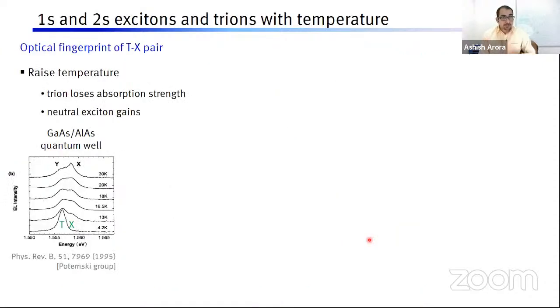For that, we use something well known from literature. In literature, it's known that if you have an exciton-trion pair, such as here, an exciton and a trion, and if you raise the temperature, then the exciton starts to gain strength and the trion starts to lose its strength with raising temperature. If this happens, it is called transfer of oscillator strength. And if this happens, that means you have an exciton-trion pair which is connected with each other.